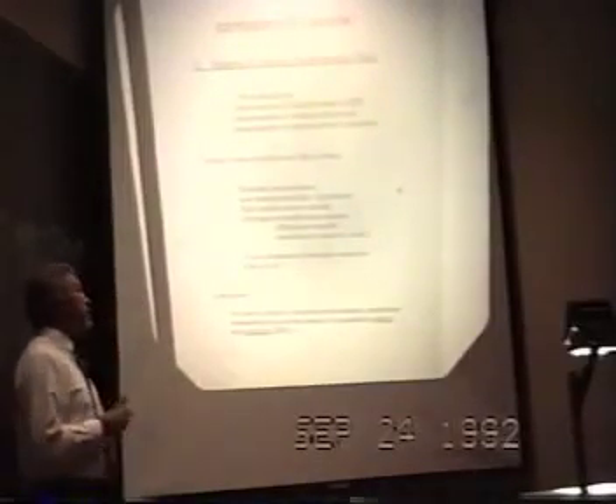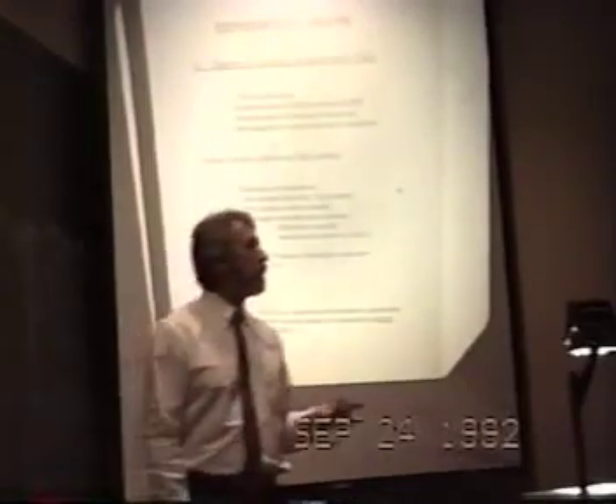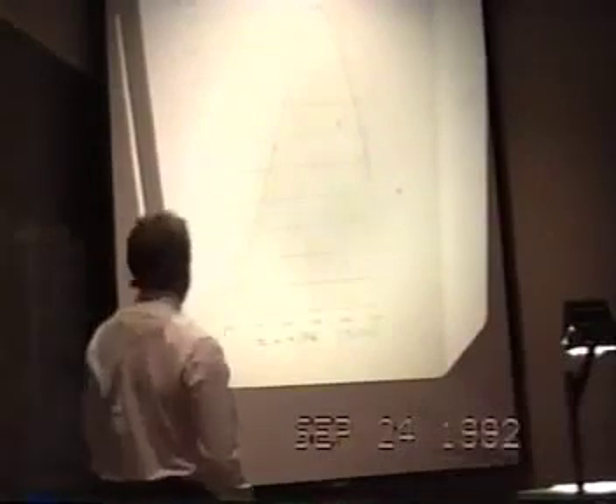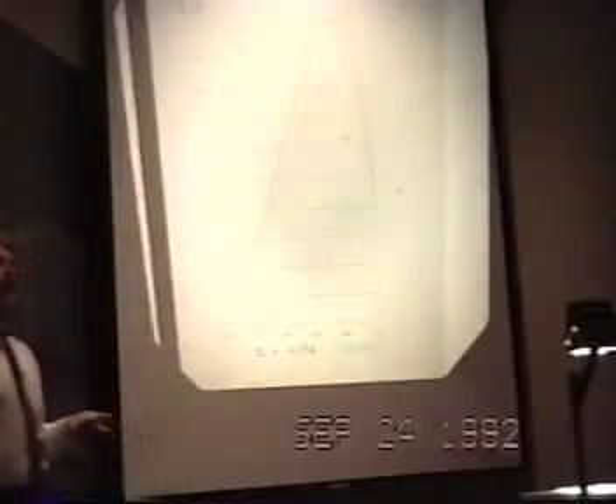By careful control of the electrode pretreatment, the electrolyte composition, and the current density, it is possible to attain and maintain the high loadings, deuterium to palladium ratios approximately 1, that are necessary to produce the anomalous effect. I'm going to talk about loading quite a lot, and I'll correlate my results somewhat with the deuterium to palladium atomic ratio.